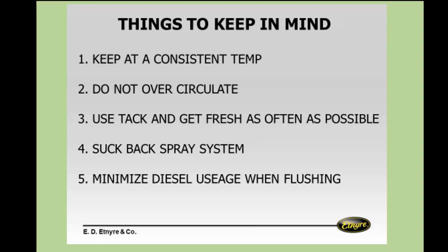So what you want to do is get that tack out of the tank as often as possible and refresh it. Try to keep it in there for a minimal period of time. The more you heat it, the more you circulate it, the more risk you run of breaking it down and separating the product in the tank.